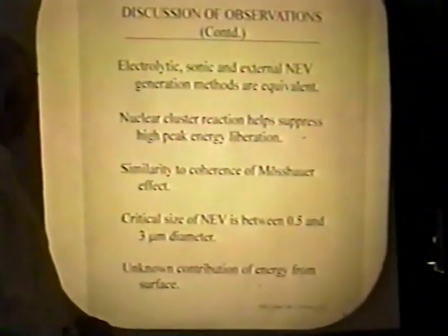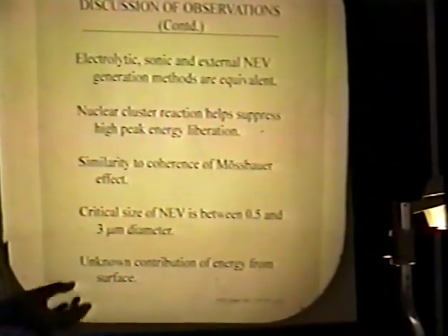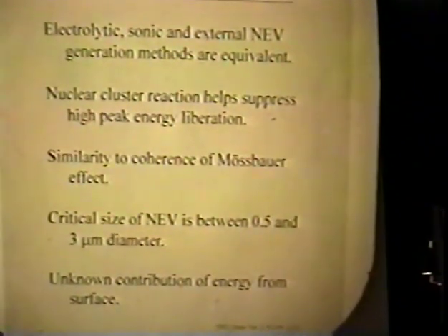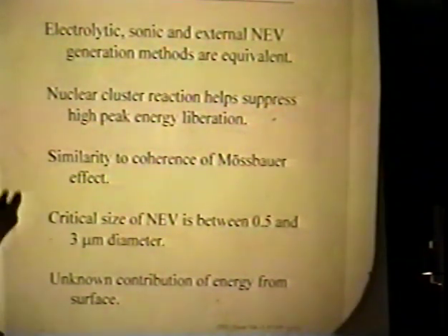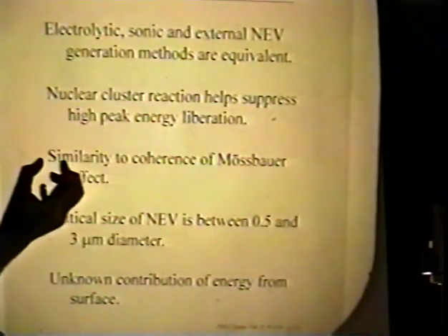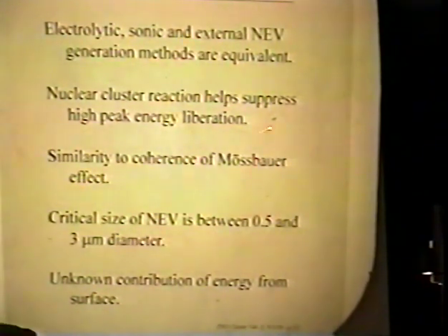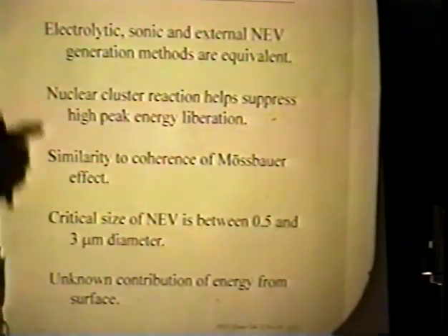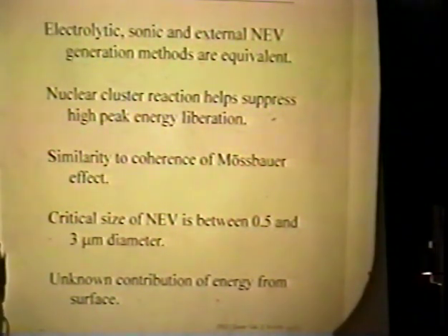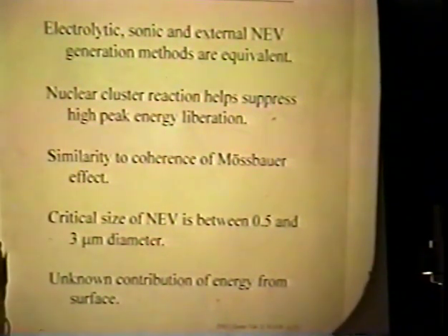This gives us an equivalence between the electrolytic, sonic, and any externally or gaseous generated NEV type process. But the wonder here is that in the nuclear cluster reaction, this clump, so much to me like a Mossbauer effect, having some form of coherence, is responsible for the suppression of all these high peak energies. That's why you don't see stuff coming out of here with gammas in it, which we do not.